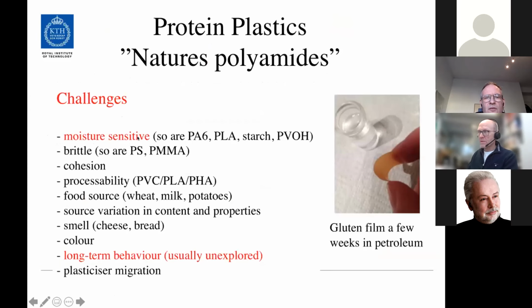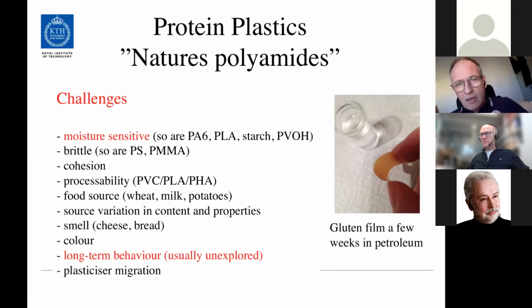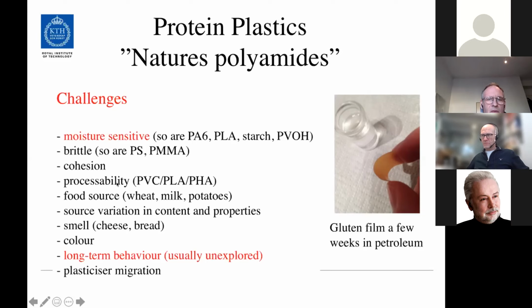There are challenges. I mentioned the high moisture sensitivity, but so are also PA6, PLA, and polyvinyl alcohol. They are quite brittle, with a few exceptions, so you normally need a plasticizer. There are exceptions from that. For example, fibroin is relatively tough, and keratin also. Cohesion could be a problem. Processability can also be an issue, but there are also other polymers which are difficult to process. Food source: a lot of these examples are actually food items, so one has to be careful when considering these materials from that point of view.